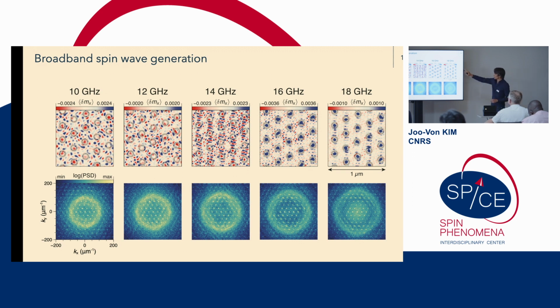We can sweep the frequency across this range shown here, and it does respond more or less well when we get into this range here. But as the Fourier transform shows on the bottom, we can selectively generate, in effect, what kind of wave vectors are being emitted by these precessing skyrmion cores. So there you go, that's the connection to the 3D magnonics through the skyrmions.